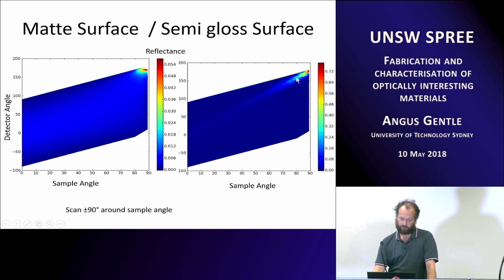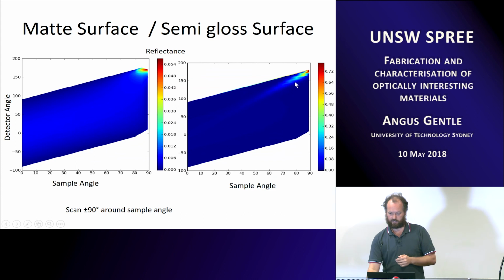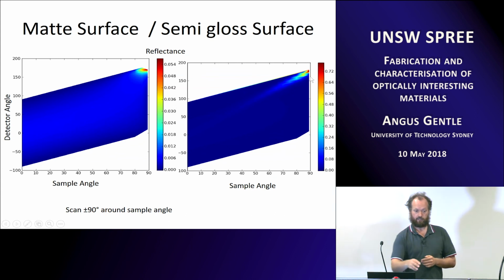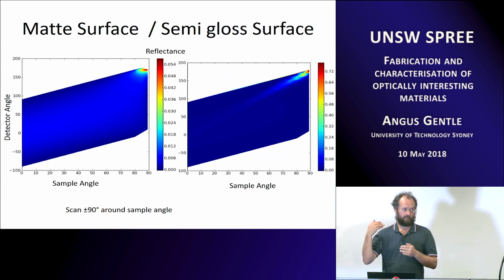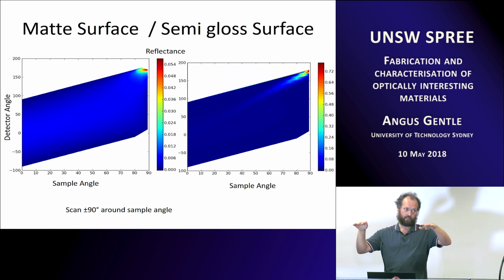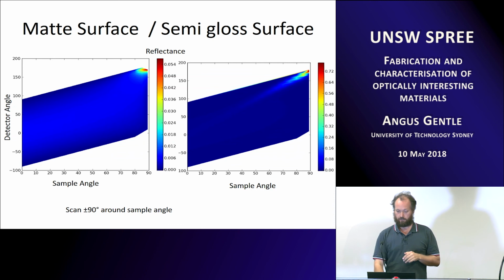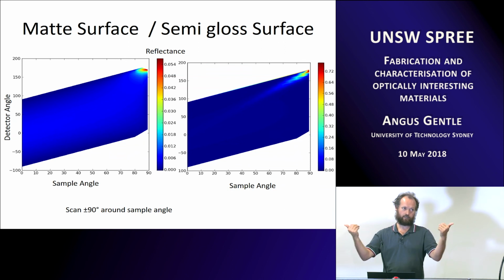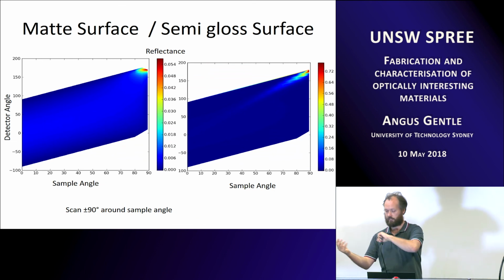This one here, you can see the specular reflectance is down the center there, and then how much scattering you get. So you can see here that, as you notice, if you see any surface that's glossy, it reflects quite high at high angles just because of the binder material that's in there on the outside. So that same thing occurs in the infrared. So if you've got a very smooth surface, it reflects highly at the high angles, so you don't emit very well. So one of the things we'll look at is the effects of surface texturing on emittance.